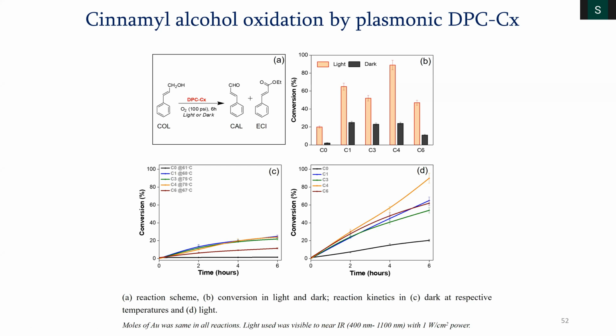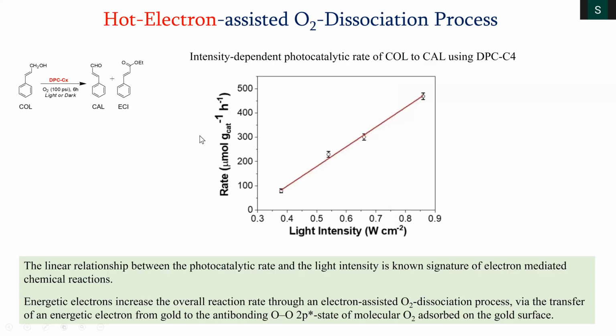Now, how do I prove this hypothesis? How do I prove that there is electron transfer from black gold to the oxygen and oxygen is dissociating? For that, we did this particular experiment. If I add more and more photons, more and more intense light onto the black gold, I should produce more and more hot electrons, and these more hot electrons will produce more dissociated oxygen, and that should increase the rate of a reaction. That's what we did.